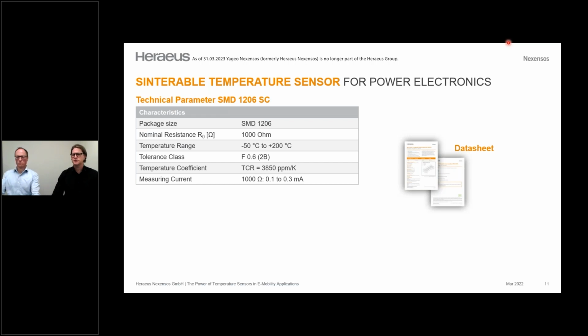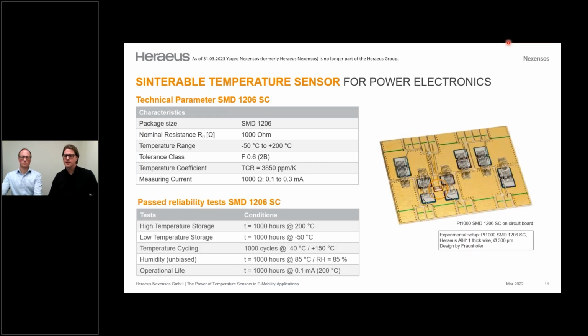Typically we produce a B version, but this is only because of some effects we sometimes see with the silver material, which is here a lot in. The TCR is 3850, and the measurement current is limited with 0.1 up to 0.3 because of self-heating effects.